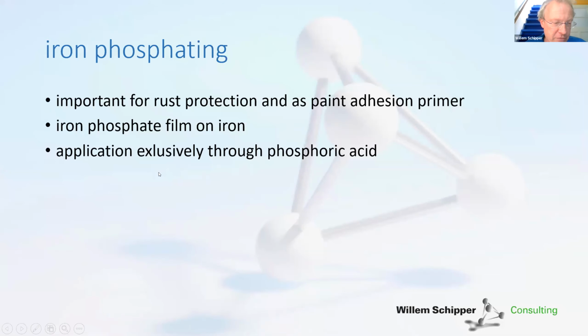To look around a bit at iron phosphate applications, you always find iron phosphating, which is a really big and very important application if you look at the size of the industry behind it. To protect iron from rusting, it's phosphated on the surface. It serves as a corrosion protector, also as a paint adhesion primer. So it is iron phosphate, but it's exclusively made through phosphoric acid acting on the steel surface. So there's no chance to actually put iron phosphate in this application.